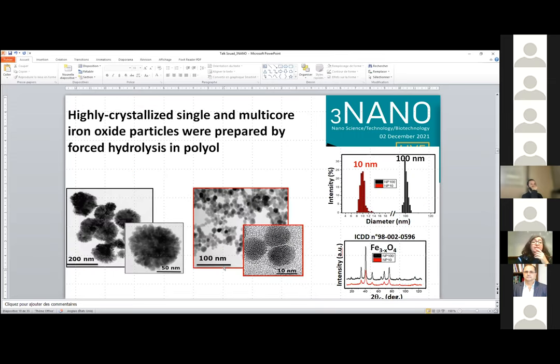Okay, so let's start with the size effect. Using the polyol process, we succeeded to produce highly crystallized single and multi-core iron oxide particles. You can see here the TEM images. So the polycrystalline particles were about 100 nanometers in size, while the single crystals were about 10 nanometers in size. And both exhibit the spinel iron oxide structure, as you can see here, with a chemical composition comprised between that of maghemite and that of magnetite. It's for that reason I wrote Fe3-xO4 as the chemical composition of our particles.